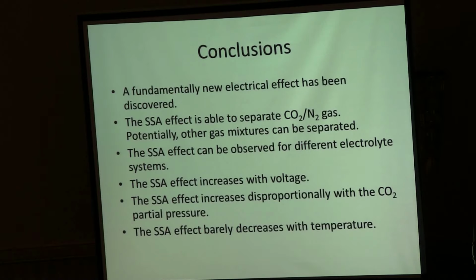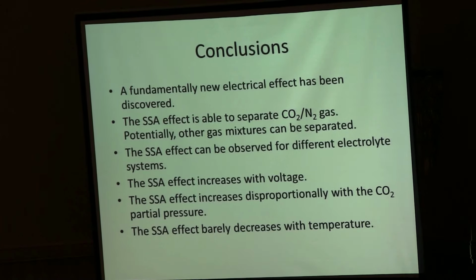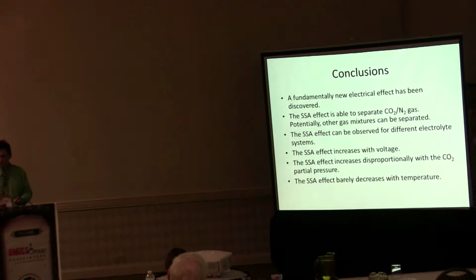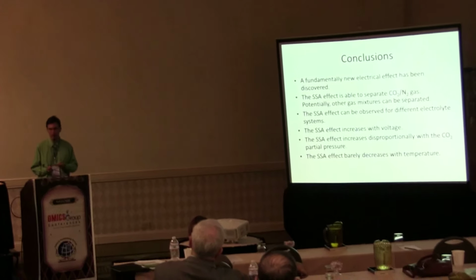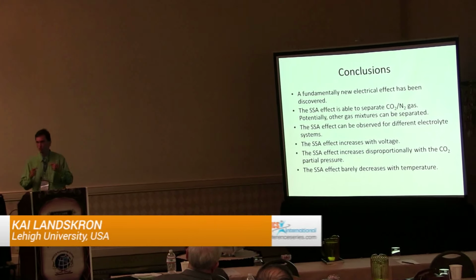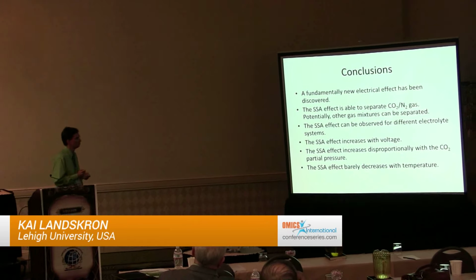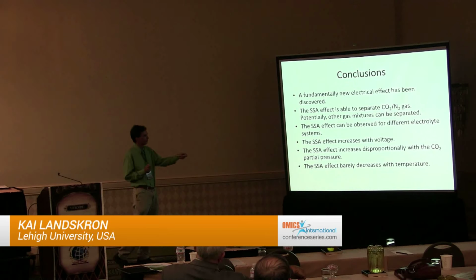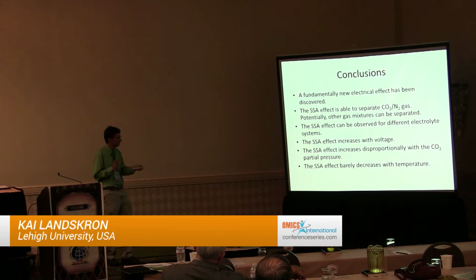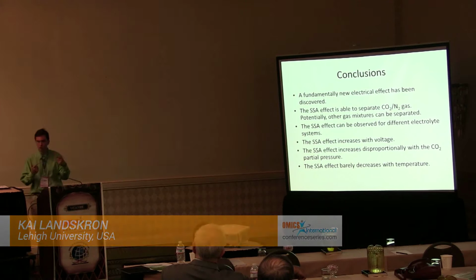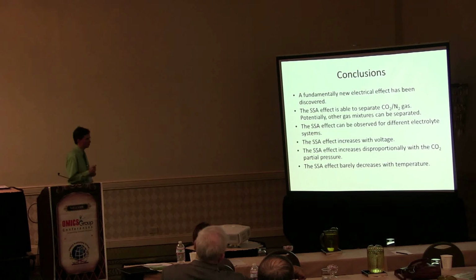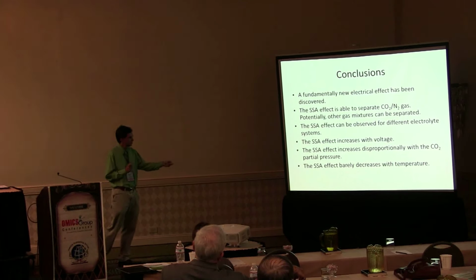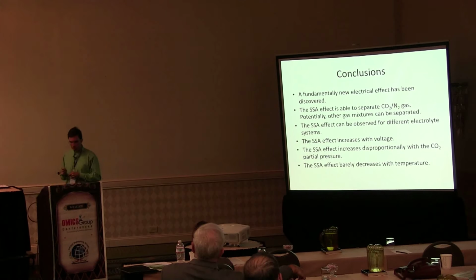So that brings me to the conclusion that we have discovered a new electrical effect, the supercapacitive swing adsorption effect. It is able to separate carbon dioxide from nitrogen, potentially also other gas mixtures, as this effect may not be unique to carbon dioxide. It can be observed for different electrolyte systems. It increases with the voltage, and it increases disproportionately with the CO2 partial pressure. It also barely decreases with the temperature.